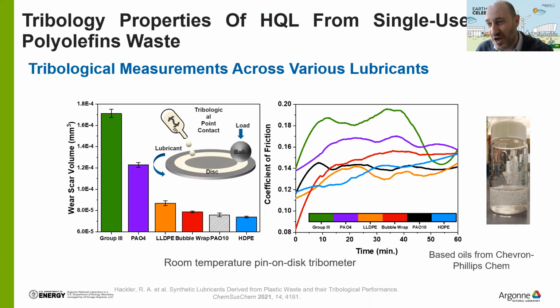And you know how much it costs to replace the oil, if you want the synthetic oil, that is roughly $100 per gallon of oil. And the 4 and 10 is the viscosity of the oil, and it depends where you live. In Chicago, it's very, very cold in the winter, so we need a polyalpha olefin 10. If you're in the south, you need a polymer with less viscosity, and so on. And then we compare the lubricant oil that we obtain from plastic waste, and benchmark it against the state-of-the-art lubricating oil on the market. Very, very interesting.